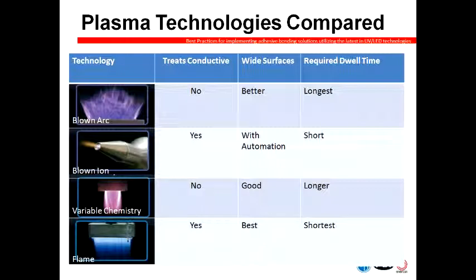So to summarize the technologies quickly, blow and arc systems are not good for conductive materials, but they're good at wide surfaces and require the longest amount of dwell time. Blow and ion systems can treat conductive and non-conductive materials. They can treat wide surfaces with automation or multiple heads, and they require a short amount of dwell time. Variable chemistry plasma are not able to treat conductive materials. They're good with wide surfaces and do tend to require a little bit longer dwell time. Flame plasma systems will treat both conductive and non-conductive materials. They're great for wide surfaces in that we're able to build a wide variety of burner sizes, and the amount of dwell time required by them is very short.